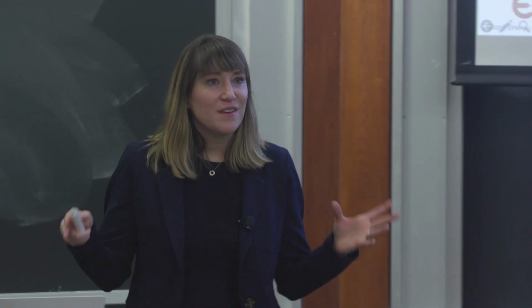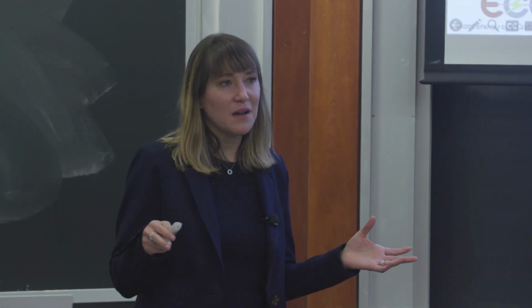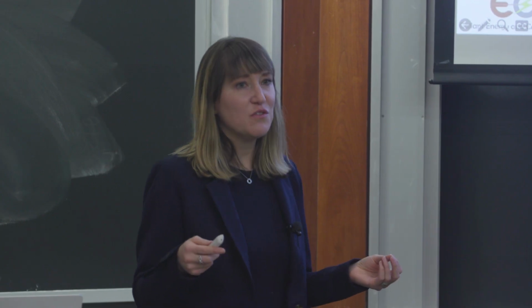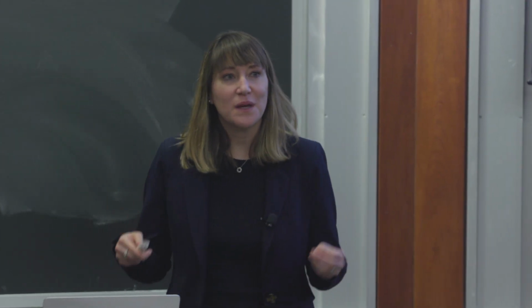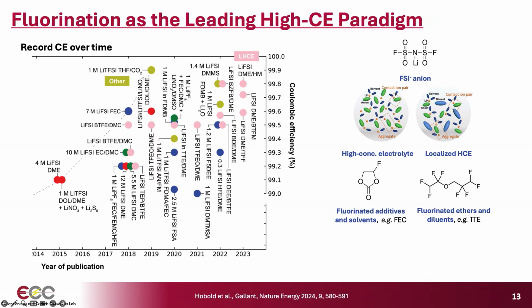And now armed with this set of capabilities, what we were really interested in doing is looking broadly across the electrolyte space and looking for which SEI phases correlate most strongly with Coulombic efficiency, okay? So this graph here shows the record Coulombic efficiencies achieved in the field over time. There are a tremendous number of acronyms here, and I don't expect you to process all of them. So I'll summarize. The key thread in all of these is an overwhelming reliance on electrolyte fluorination.